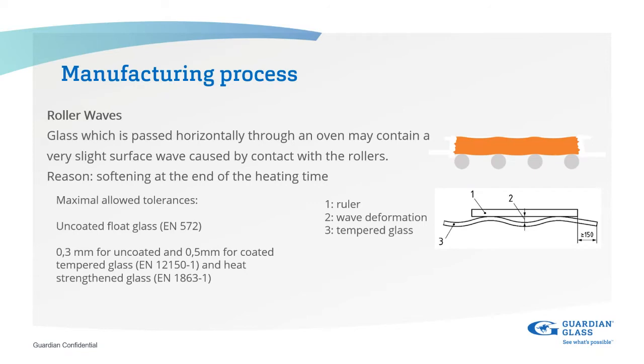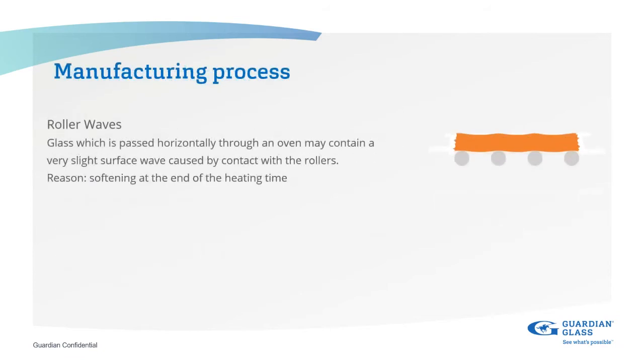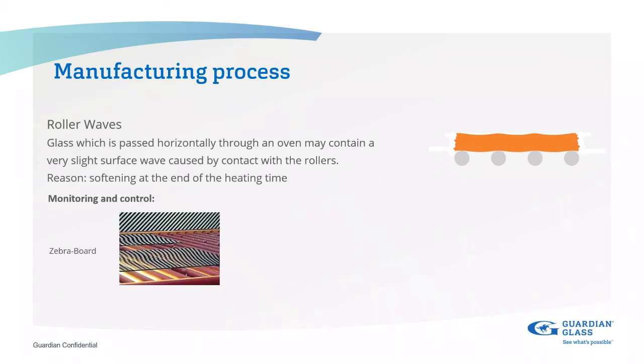The way to measure roller wave is by a simple ruler which will measure the wave deformation from peak to valley, and it is more apparent in the tempered and heat strengthened glasses. Glass which is passed horizontally through an oven may contain a very slight surface wave caused by contact with the rollers, as we mentioned earlier.